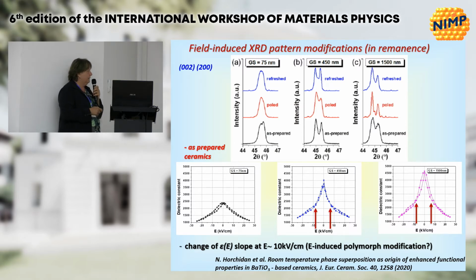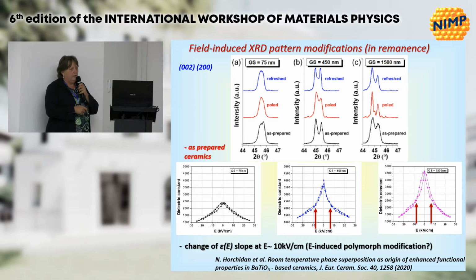So my colleague Cristina Ciomaga studied a bit the role of poling in changing this phase superposition, at a qualitative level without calculations. I will explain why. Because we observed in the tunability data, I give here some specific grain sizes, that there is a change in slope at a DC field of about 10 kilovolts per centimeter. So she poled these samples with the same field level at room temperature, and as you can see, after poling, or as a prepared sample, they look different. So if we have a range of phase instability, by applying a field, or like other people did, by poling, they could change the phase.